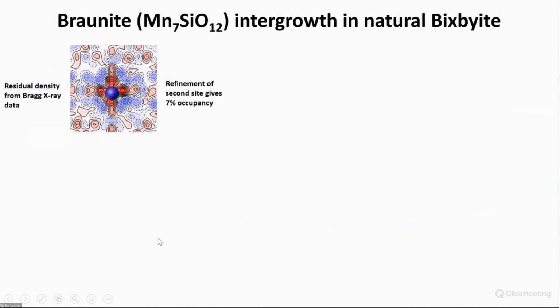But then you can do your residual density from the X-ray refinements, and you see there are some extra peaks near the metal sites. You can refine it, as I did before. It gives about 7% occupancy. But what is really the structure of Bixbyite?